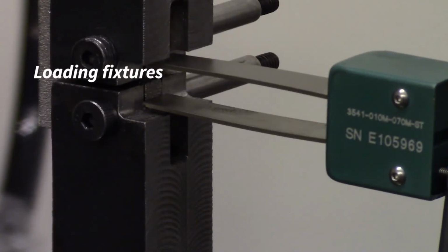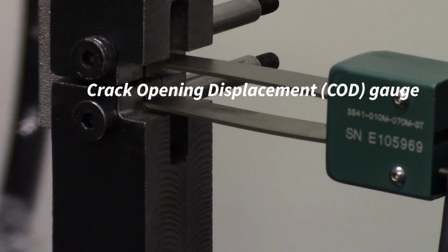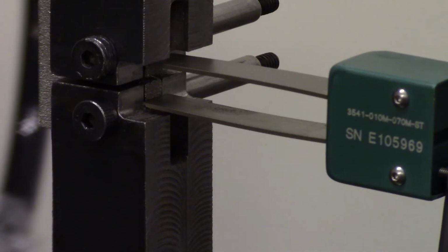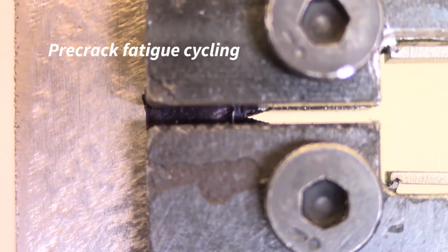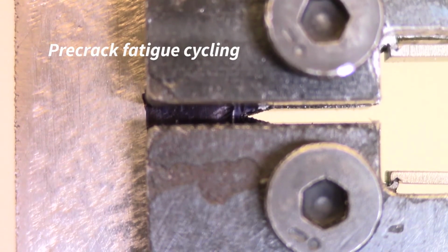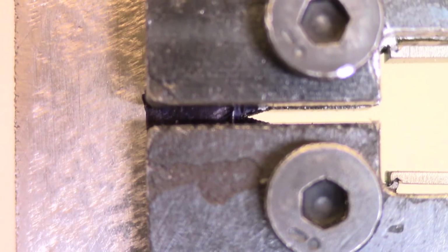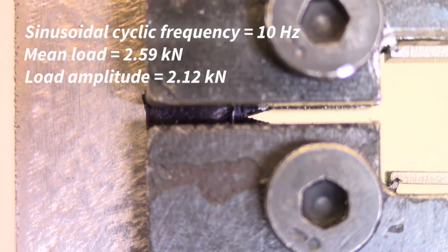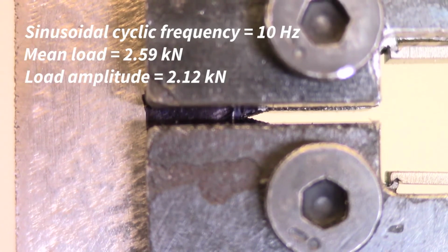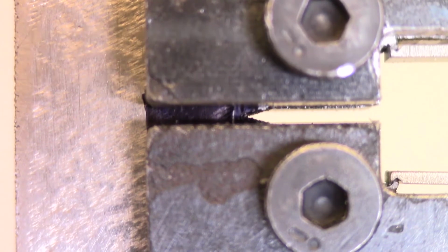So that is the configuration. We have our clip gauge installed, specimen ready to go. I'll get the data acquisition set up and we'll start pre-cycling. So we've begun our fatigue pre-cracking. Here's a close-up of the notch area. You can see our vertical line there, the silver line. And you can see that we're cycling at 10 hertz, 10 cycles per second. So we'll keep this up until we get a crack that develops all the way to that vertical line.